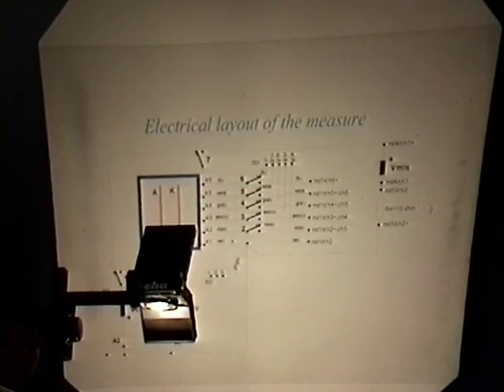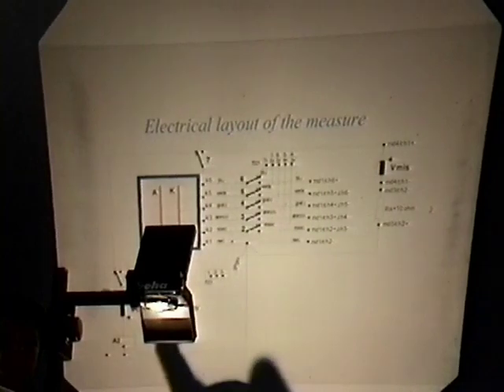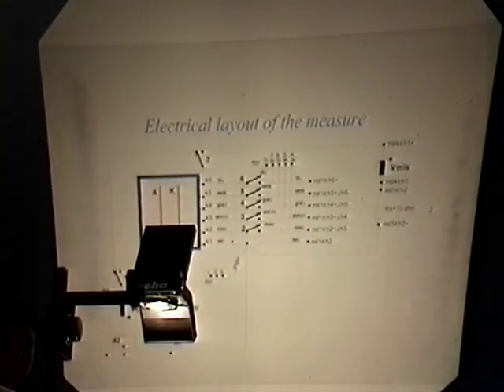What is difficult to measure in this configuration is the real loading of the sample. We want to measure the loading using, as usual, the R over R0 curve, the Baranowski curve, that relates the loading to the electrical resistance. But it's not easy to measure the electrical resistance of such a strip, which has a very high resistivity when dipped in electrolyte, because the electrolyte has a conductivity itself. So we developed this kind of circuit based on several relays that disconnect the electrolysis circuit during the measurement of the resistance. So there is no leakage of the measuring current into the electrolyte and vice versa. There is no coupling between the two circuits, the electrolysis circuit and the measurement circuit. This is what we have.